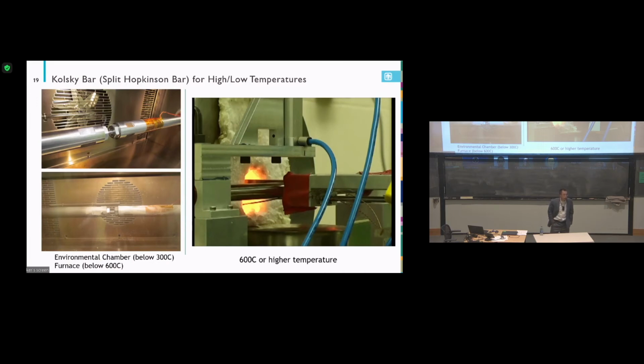Very straightforward. But when we run the high temperature, that became really challenging, because you heat the sample to a very high temperature, and the heat transfers to the bars, so basically you also heat the bars. And we don't want the bar to be heated to a very high temperature. Modulus is going to change, mechanical impedance is going to change, they're going to disturb wave propagation, and sometimes you may damage your bar. But it doesn't mean we don't have that need. We have to think about how we do that.